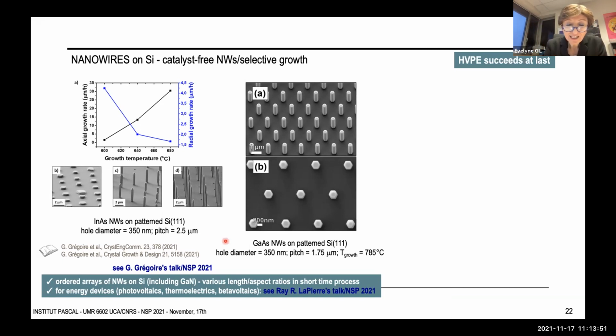So when it is performed on patterned substrates, you can get ordered arrays with various lengths and aspect ratios for various pitches in a short-time process by taking advantage of the crystal growth anisotropy of the III-V, here for indium arsenide and here for gallium arsenide nanowires. You will have more details about these arrays of indium arsenide and gallium arsenide nanowires on silicon this afternoon with the talk of Gabin Grégoire.